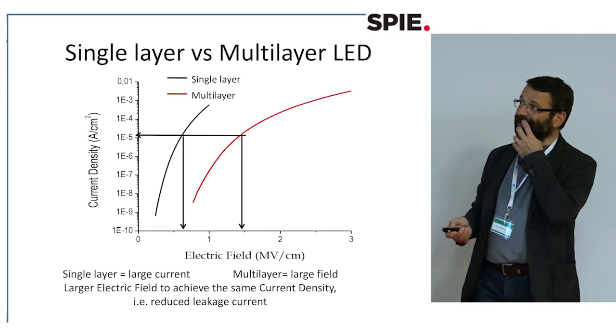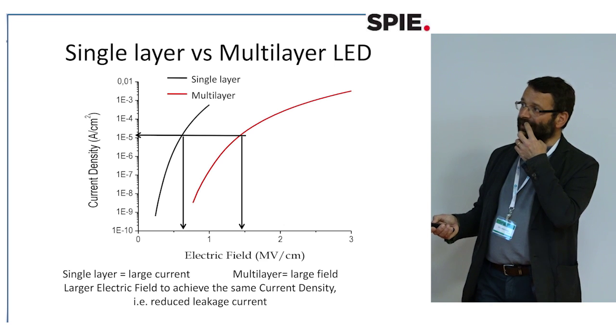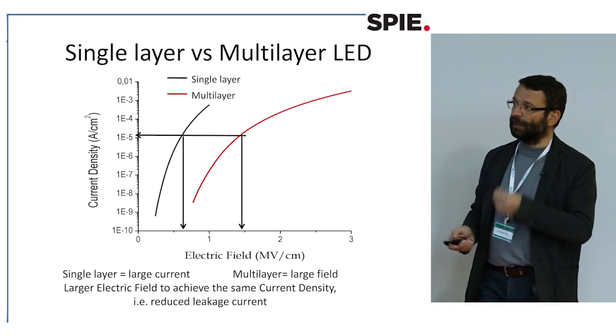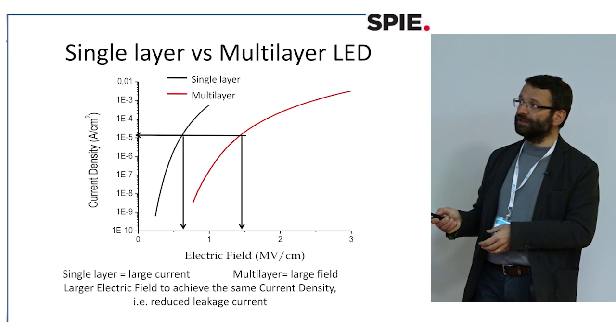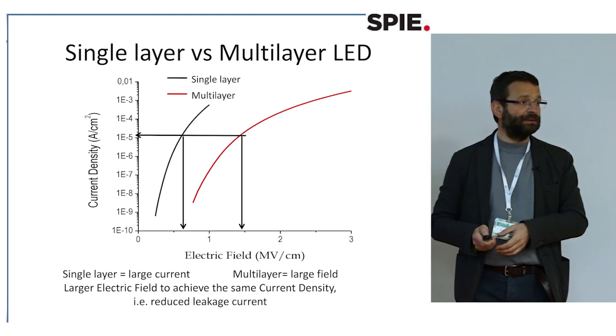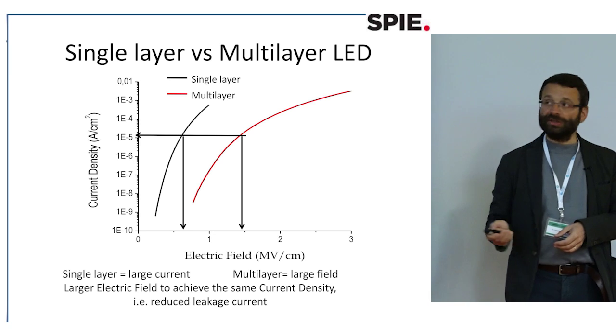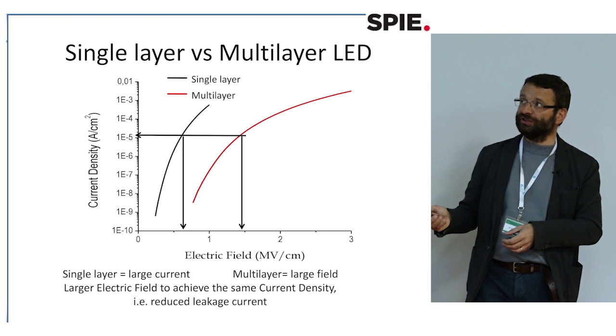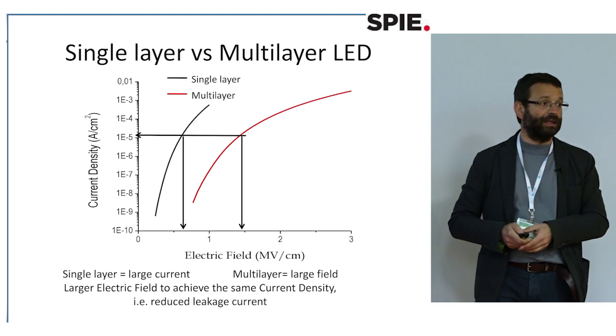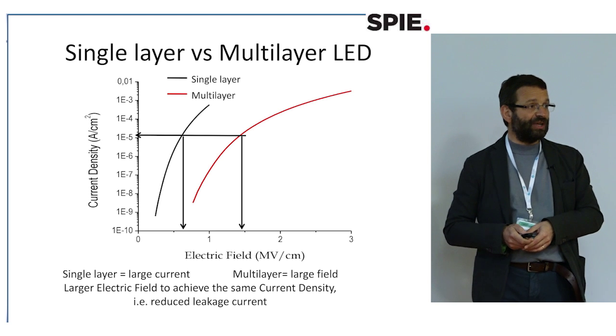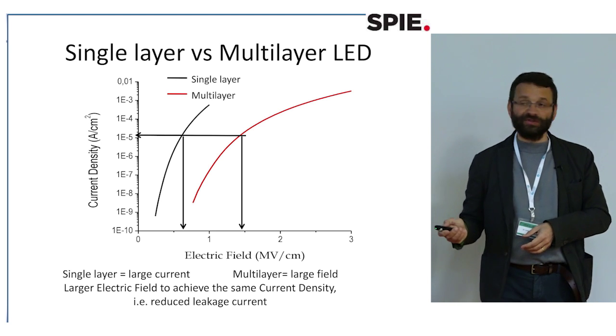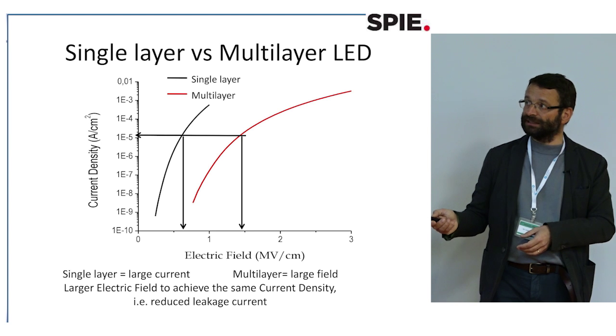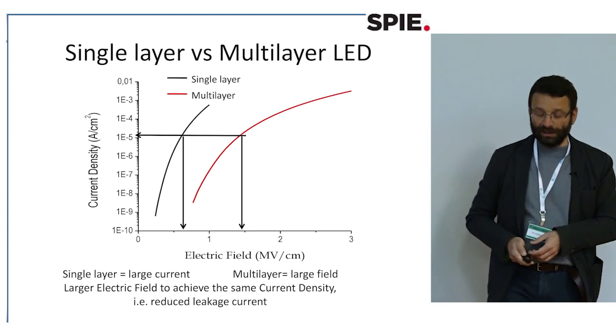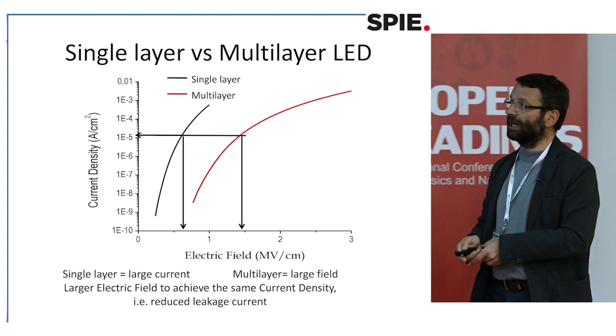So here is the result. These are the IV characteristics, so current versus the applied electric field, for the single layer and for the multi-layer. What you notice here is that you get less injection in the multi-layer than in the single layer. But this is not bad, this is good. That means that here you have huge shunt paths that, for a very weak applied electric field, cause the injection of a large current.